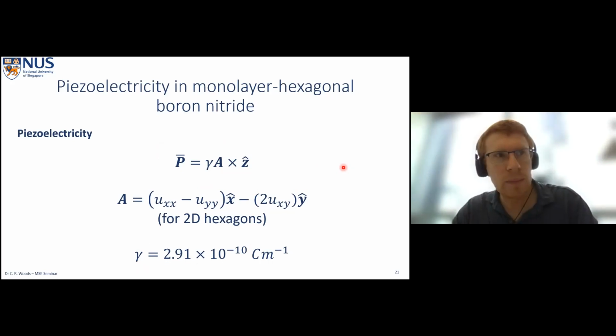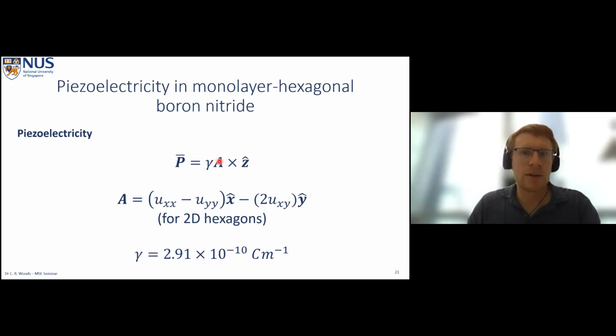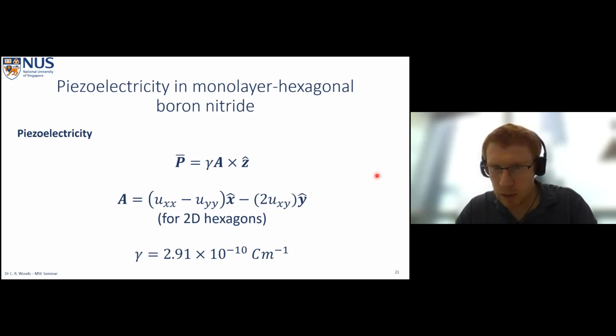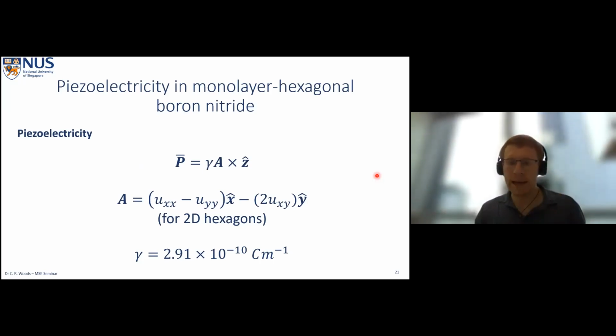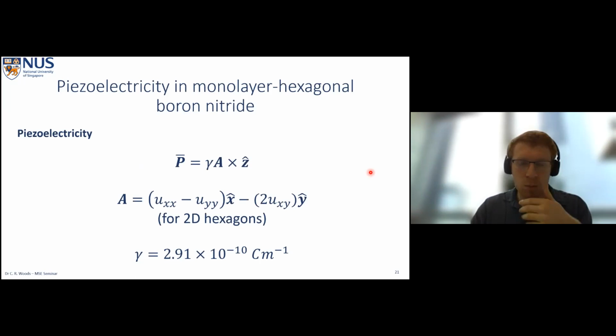And now, if you remember what I said before when we were talking about molybdenum disulfide, we have a bit of a problem because this cross product limits us to polarizations which are in the plane. So if we think about putting monolayer boron nitride and trying to exploit this piezoelectricity as part of a van der Waals heterostructure, what we would like is that this affects adjacent layers. We'd like to be able to put it in and use all of the material to affect adjacent layers and to see these properties propagate in the Z direction. So we need another way in which to do this, another mechanism for affecting those layers.